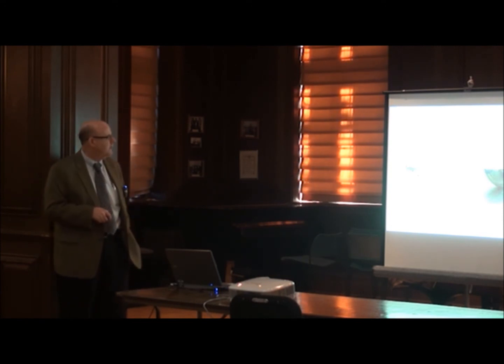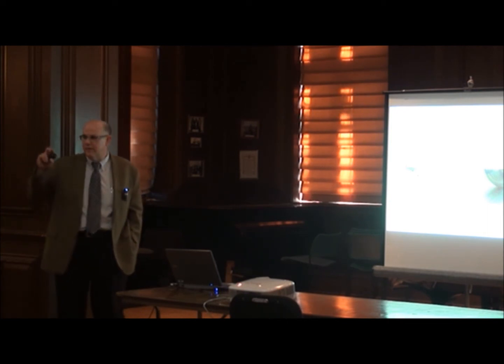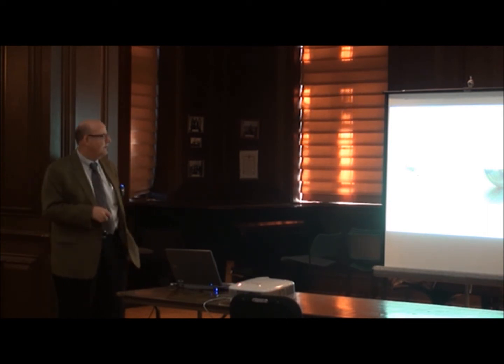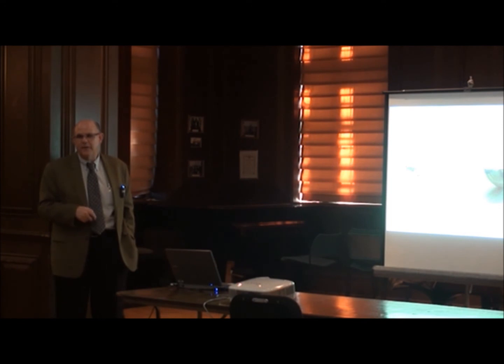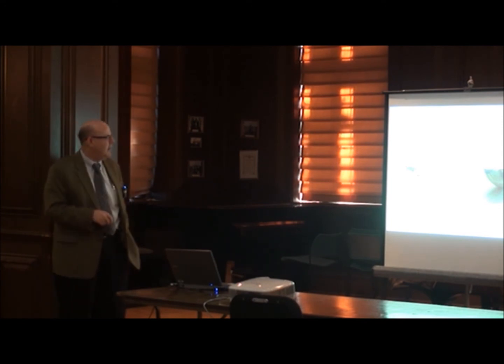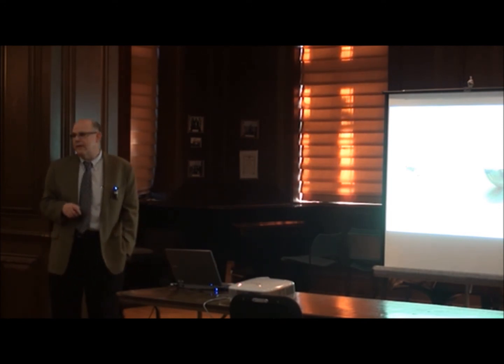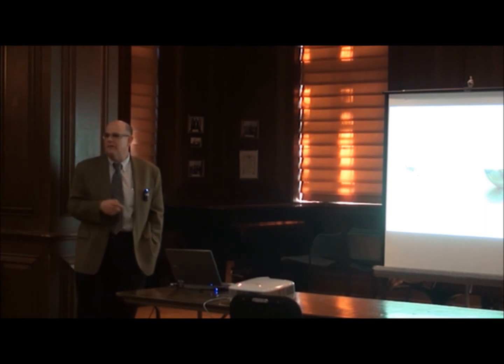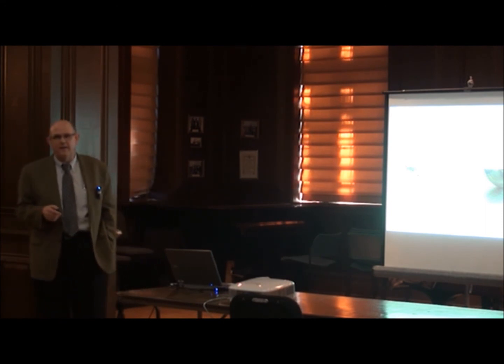And so their friction is going to drop quicker than the other ones. And as you go fast enough, the film thickness gets so large that all the lambda ratios are much greater than 5 or 6. And so the surface roughness really begins not to matter as you go out into that speed. So you can see this nice, basically summary of all the things we've talked about,